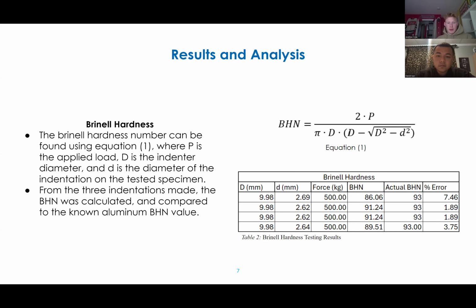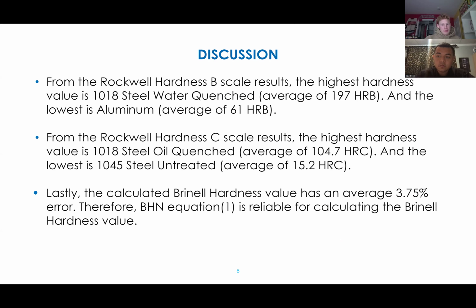And for our Brinell hardness number, using this equation over here, equation 1, where P is the force, D is the indenter diameter, and the lowercase d is the indentation diameter, we were able to calculate the Brinell hardness number for each of our trials. So from this, we got values of 86.06 and two values of 91.24. Comparing that to the actual Brinell hardness number of 93 for an aluminum alloy, we were able to yield percent errors of 7.46, 1.89, and 1.89, and that gave us an average percent error of 3.75%.